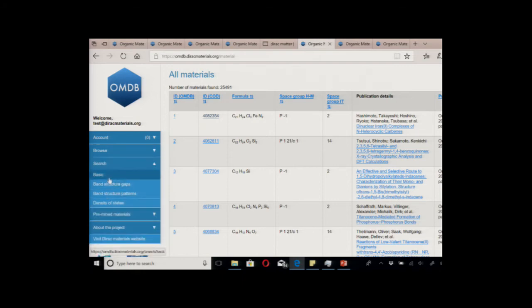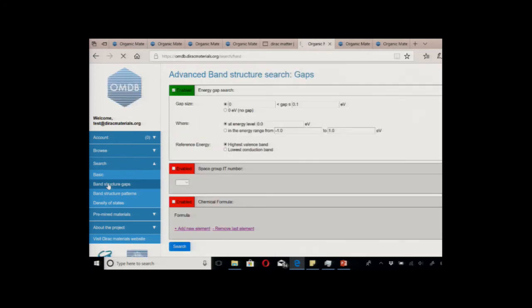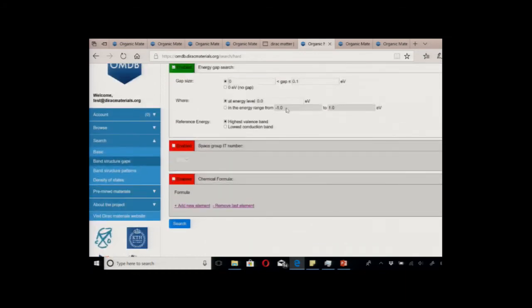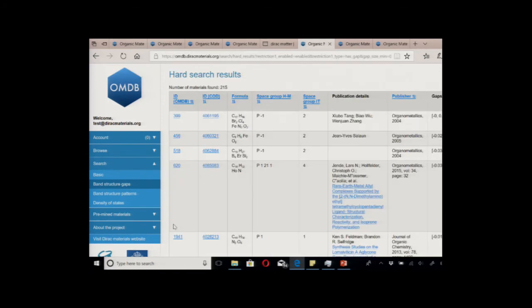So the database allows you to do structured searches. For instance, we can look at the band gaps. If I go in on this side for the band structure, for the gaps, and I ask for the set of materials with gaps between 0 and 0.1, calculated at the chemical potential, then we'll see how many we find. We find about 215 compounds which have a very small gap of about 0.1 electron volt.